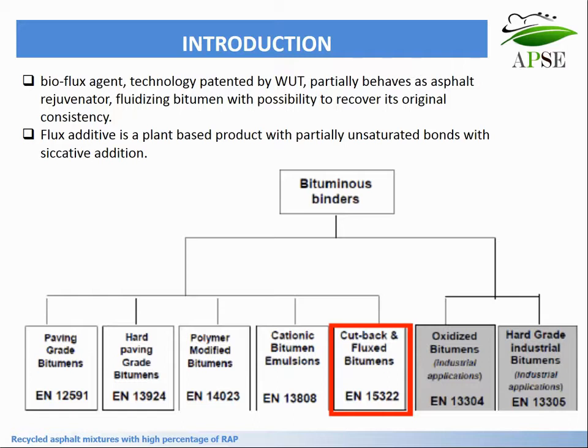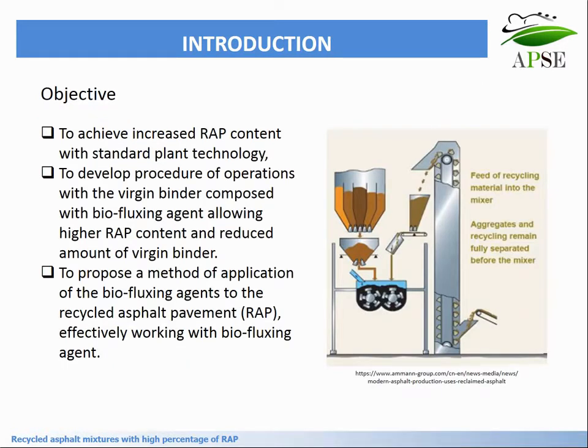The bio-flux agent is a technology patented by Warsaw University of Technology before the project started. The idea is that bio-flux partially behaves as an asphalt rejuvenator, fluidizing bitumen with the possibility to recover its original consistency. The flux additive is a plant-based product with partially unsaturated bonds with siccative addition. The objective was to achieve increased RAP content but with standard plant technology, without special modification in the factory.